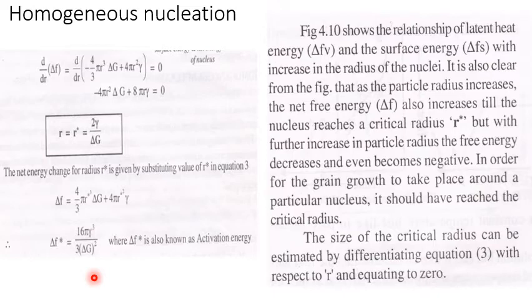Until the cluster of atoms which come together reaches this critical radius, they will not grow further. In order for the nucleus to grow further, it has to reach this r star, and we need to supply this activation energy. That is the activation energy required for further growth of the nucleus. So that is exactly what we are saying about homogeneous nucleation.